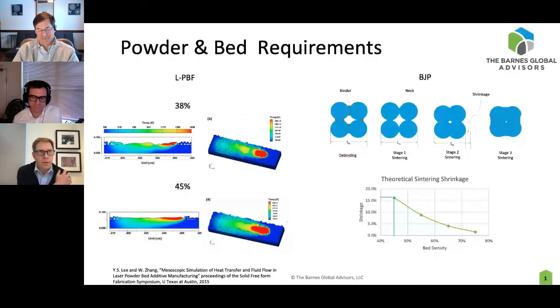I think what impacted me when I was fortunate enough to do that study with Carnegie Mellon and X1, with Dan Brunemer and people, when we looked at the results on the X1 line, depending upon how you look at the results, one thing that was interesting is that you have a direct impact on the surface, no pun intended, but then you have basically a shearing impact at all the layers below it. So as that pressure wave hits those first couple particles, it then starts to impact all the particles below it for maybe 100 microns.